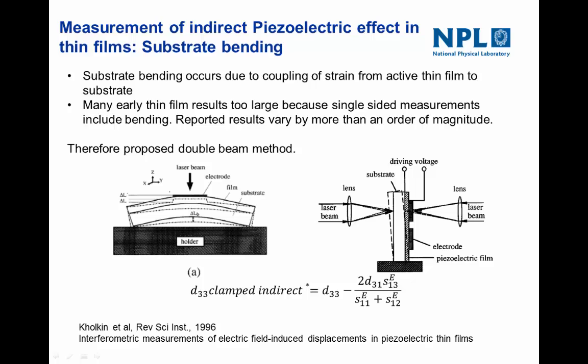If we remove that final constraint and allow the base of the substrate to move vertically, the substrate will start to bend — as shown in this schematic from a paper by Kholkin. That's what a lot of people in the early days couldn't understand: that one micron of PZT could actually force 500 microns of silicon to bend. This resulted in people making measurements where they got piezoelectric coefficients much higher than expected, because they were measuring the change in thickness of the sample plus this bend, overestimating the results.